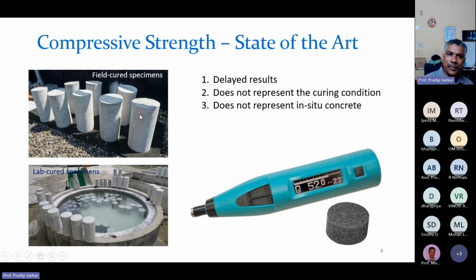So the specimens that we are testing do not represent the correct curing condition, and do not represent the in situ concrete. Many times it so happens that the concrete in the structure is separately made, and the specimens are taken from a separate mix. So they are not representative of the actual concrete that is in the structure.